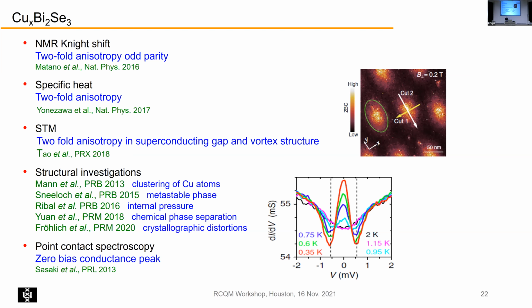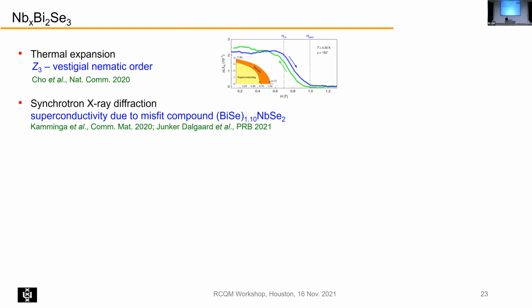So now let me conclude with niobium bismuth 2 selenium 3. Thermal expansion experiments have been performed, and they claim that there is what they call vestigial nematic order. So this is the field, this is the length change, here's the superconducting region, but above the superconducting state, there is already some breaking of the symmetry here. But that has not been confirmed by other groups.